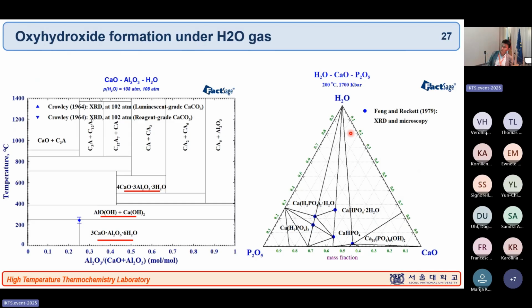And now this is the phase diagram for the very high pressure H2O environment. For example, this is the CaO-Al2O3 binary system at 100 atm partial pressure of H2O. So see here, instead of CaO-Al2O3, some other compound, you can start to see some hydroxide formation. Then it changes and can form another hydroxide. And above this temperature, you don't have any hydroxide. We can do this kind of calculation at any pressure up to several gigapascals now. And so we can look at what kind of hydroxide can form depending on temperature.